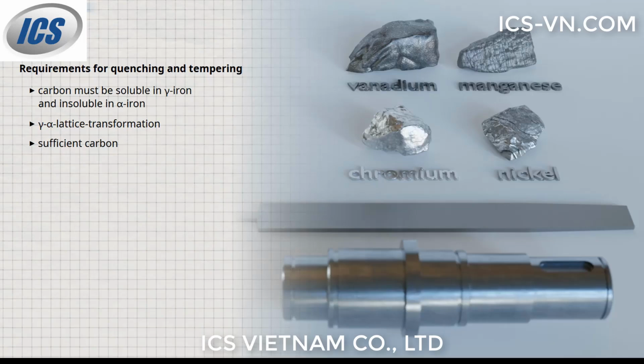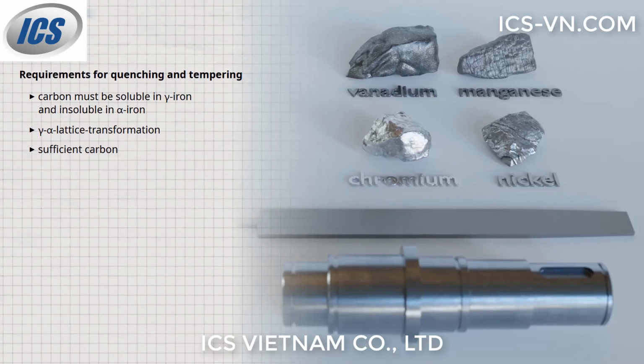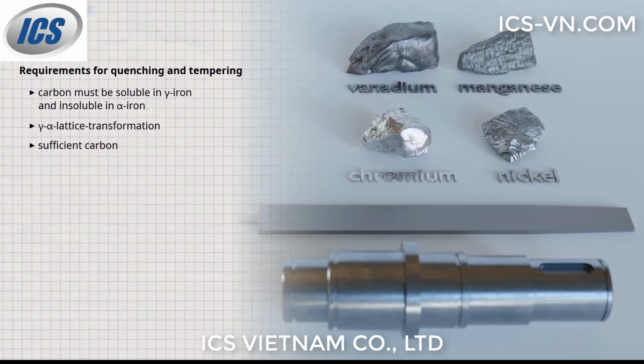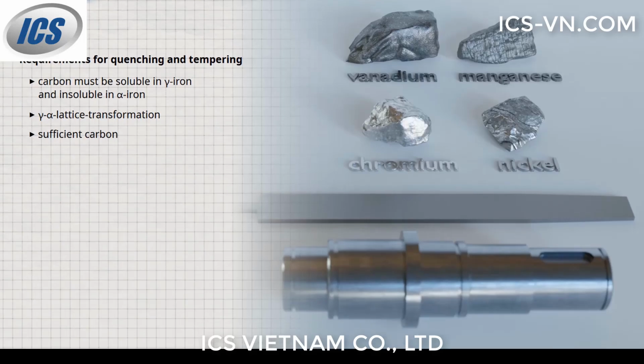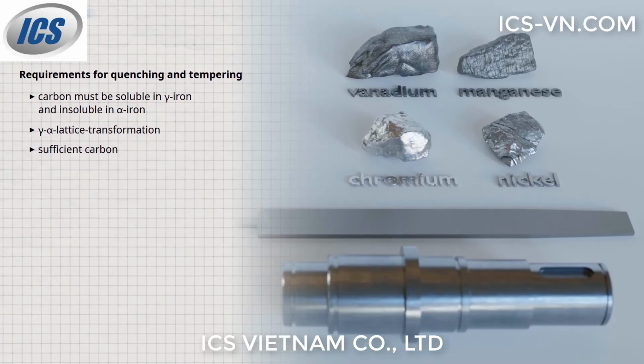Such ferritic or austenitic steels cannot be hardened because the necessary gamma-alpha lattice transformation is missing, and therefore no martensite can form. Another prerequisite for the hardenability of a steel is a sufficiently high carbon content.